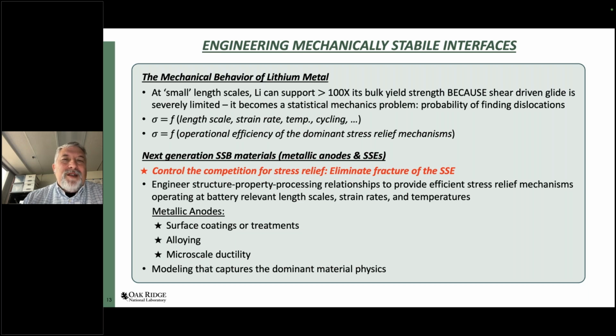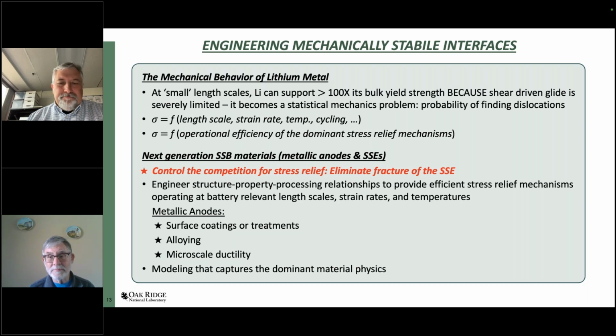The last point I'll make is that we obviously need modeling tools that accurately capture these stress relief mechanisms operating not only in our anodes, but also in the separators. I didn't emphasize it, but the anode is paired with a separator. All the problems that Sergey was talking about with the separator are because of what the lithium is imposing. So the separator plays an absolutely pivotal role in figuring out how to alleviate the pressure that develops in the lithium, and ultimately how to keep a mechanically stable interface. All right, I will end it there, and look forward to your questions at the end.